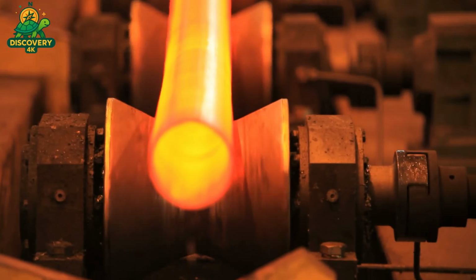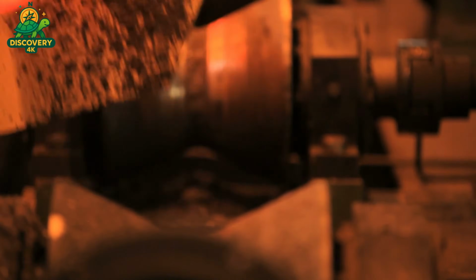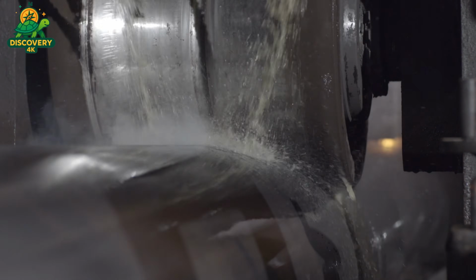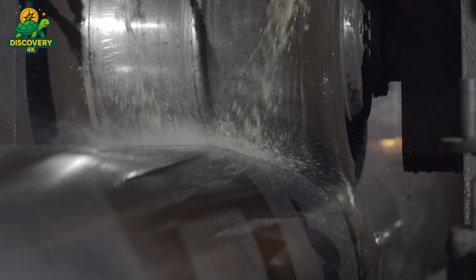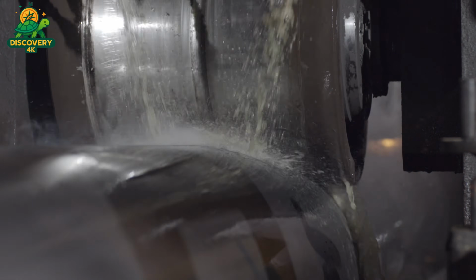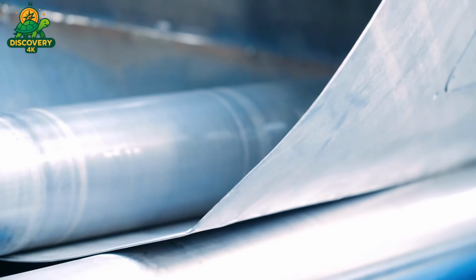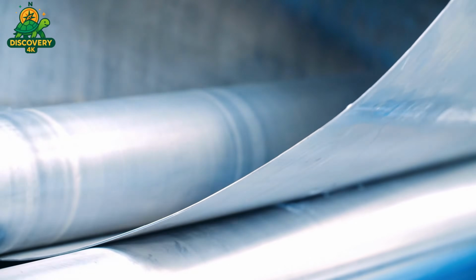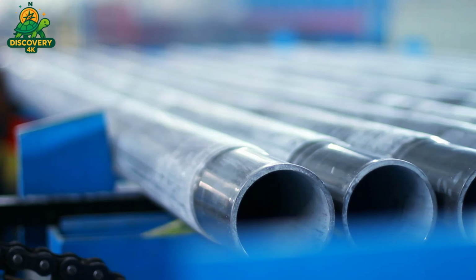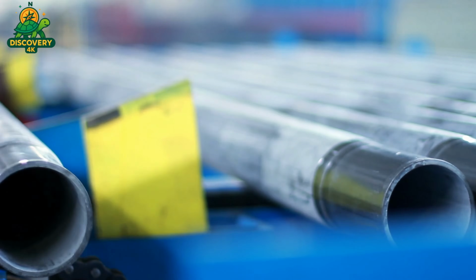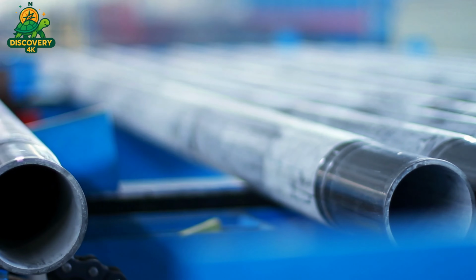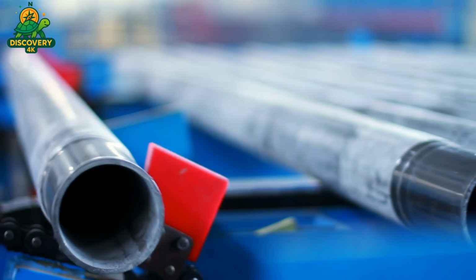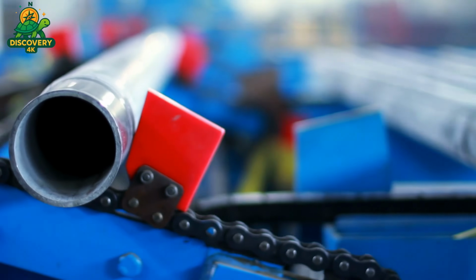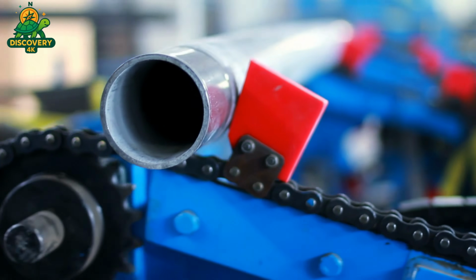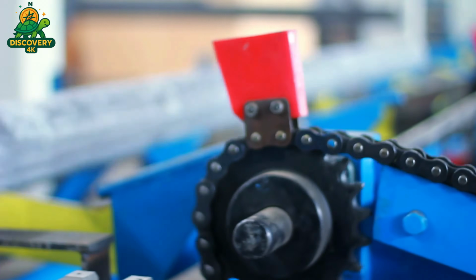To ensure every pipe is safe, reliable, and defect-free, manufacturers perform non-destructive testing, NDT. Depending on the pipe's end use, testing may include eddy current testing, which detects surface and near-surface flaws using electromagnetic fields. Ultrasonic testing sends high-frequency sound waves through the pipe to detect internal cracks or inclusions. Hydrostatic testing fills the pipe with water under high pressure to check for leaks or weak spots.